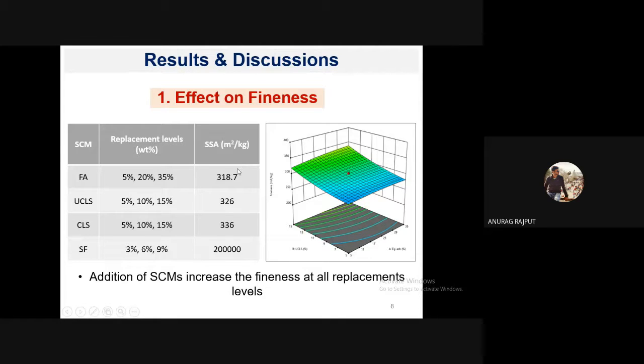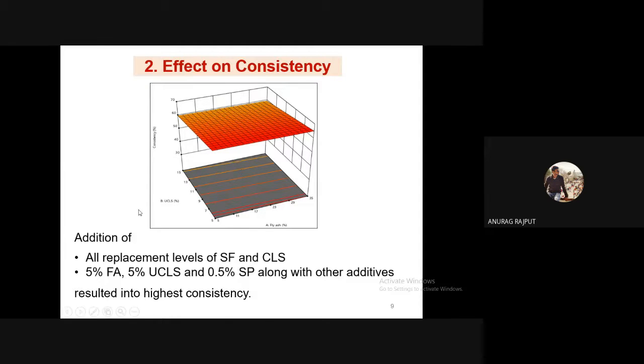And I have conducted a fineness test, and these are the fineness of each SCM. And I have concluded that by the use of these SCMs, the fineness of composite cement was increased, because the fineness of all the SCMs is very, very high as compared to OPC. So the resultant is that the fineness was increased. If we talk about the consistency, all the SCMs increase the consistency. For silica fume and calcined limestone, at every replacement level, the consistency was increased. But for fly ash, uncalcined limestone, and super plasticizer, only the dosages of 5% fly ash, 5% uncalcined limestone, and 0.5% super plasticizer result in an increase in the consistency. Whereas if we increase the dosage of these input variables, consistency falls. So these are the only dosages which can enhance the consistency.